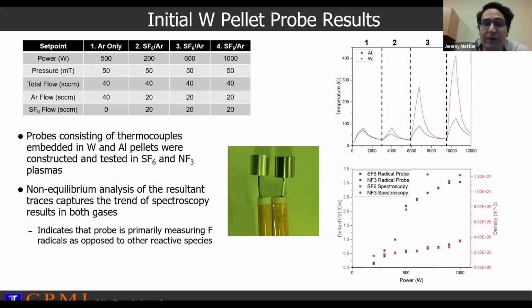Here you can see a probe pictured at center, where we have an inert probe, in this case an aluminum pellet, on one of the thermocouples, and a reactive probe, a tungsten pellet, on the other probe. When we stick these into an SF6 plasma, we actually get an incredibly large temperature response. This is much more like what we were seeing in the hydrogen case. So this is another advantage of using the larger pellet style design. And so here we're actually getting